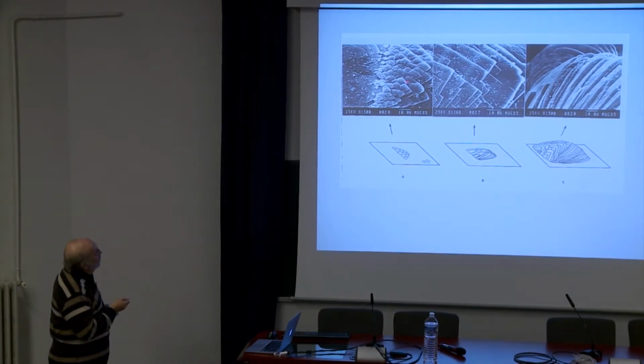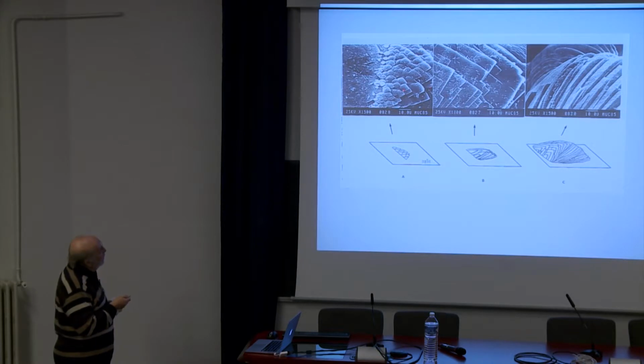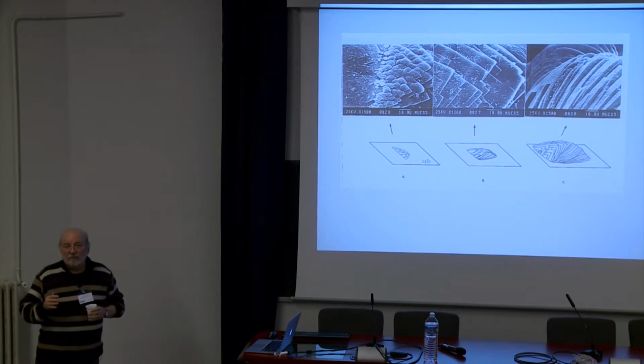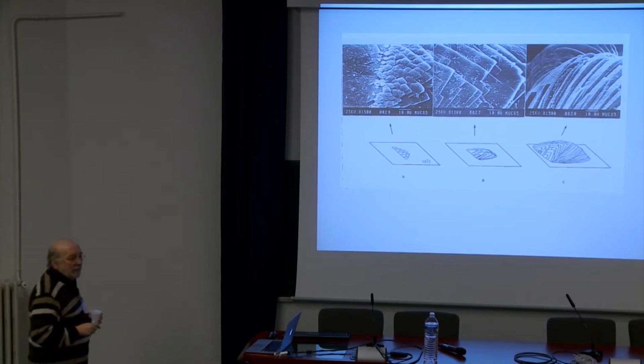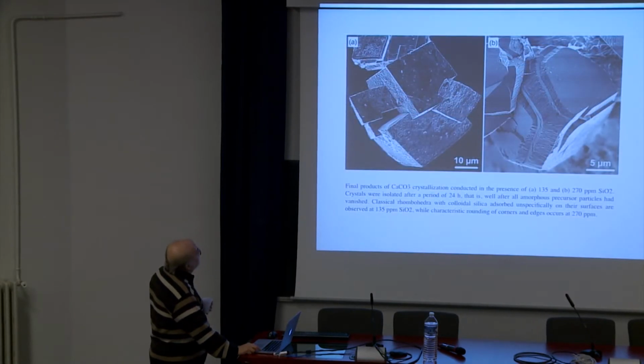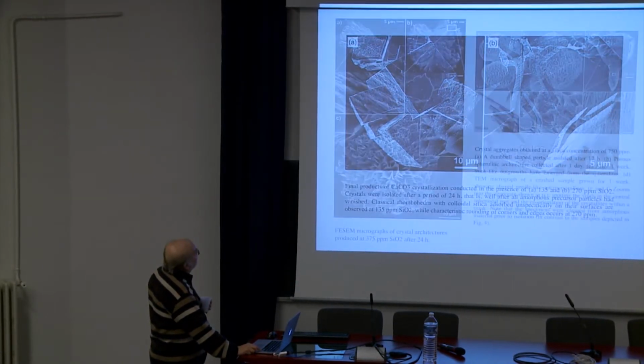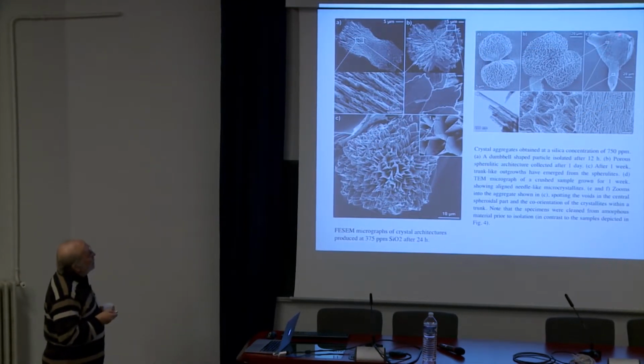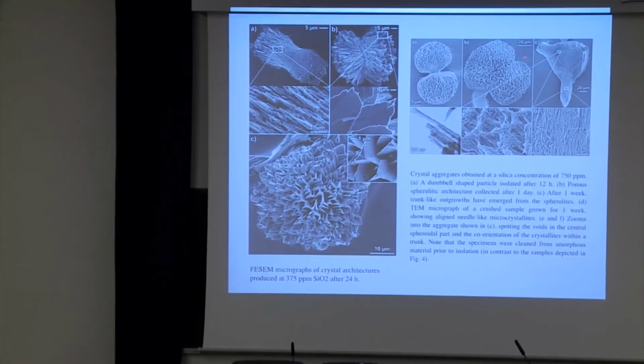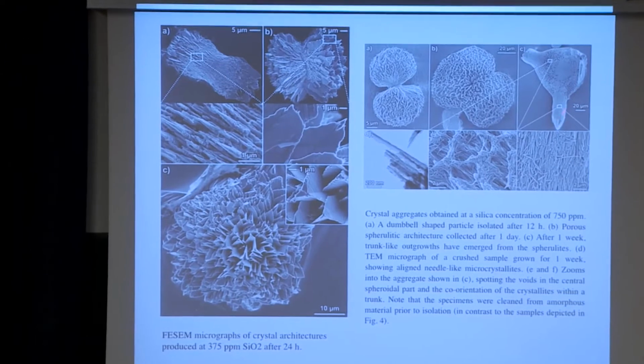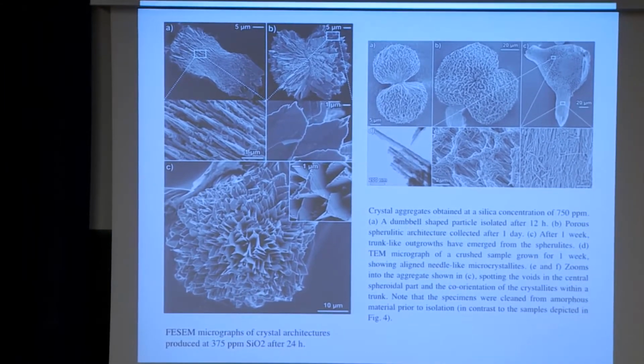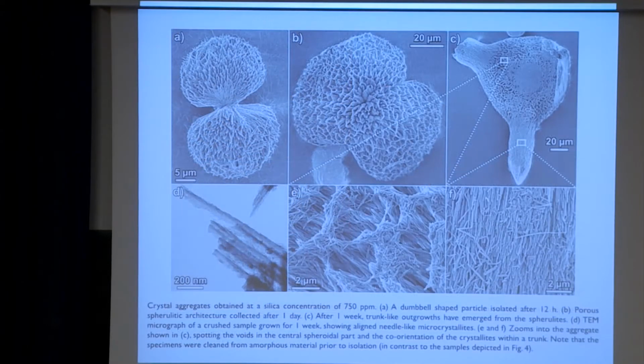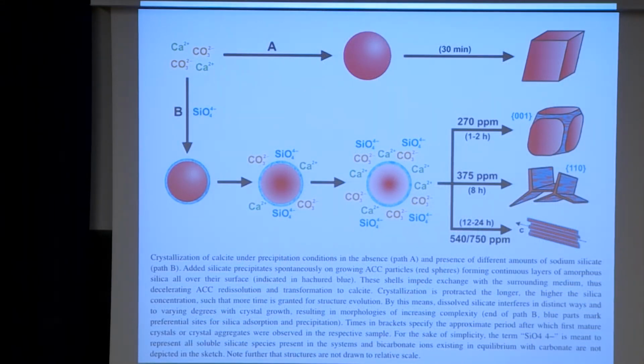Okay, we have this kind of growth that we don't understand yet very well. But this is a kind of growth which mimics perfectly what happens in biomineral formation. This is another example of just an initial rhombohedral phase that finally has these six branches that relate to the original 104 phases of the calcium carbonate. See? So we have proposed a mechanism that, well, I think this is not really explained because we don't know exactly how it occurred.